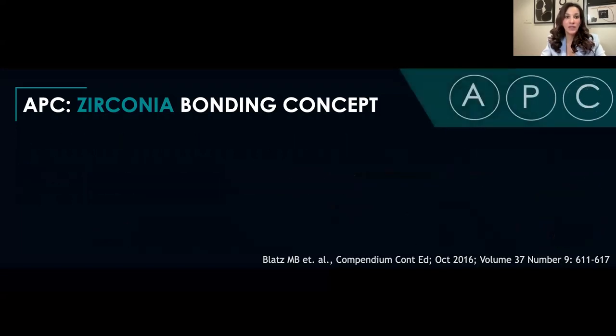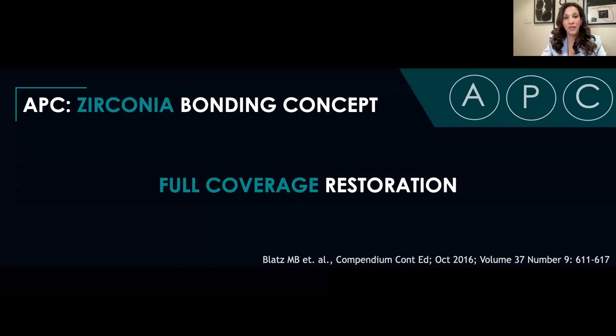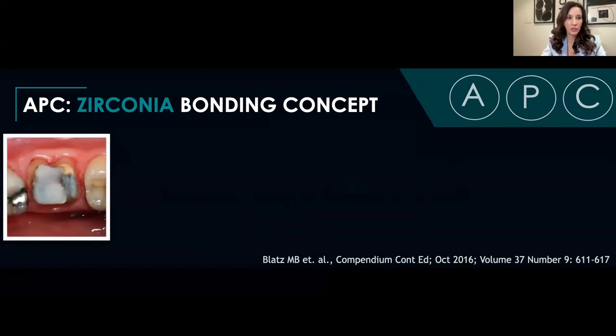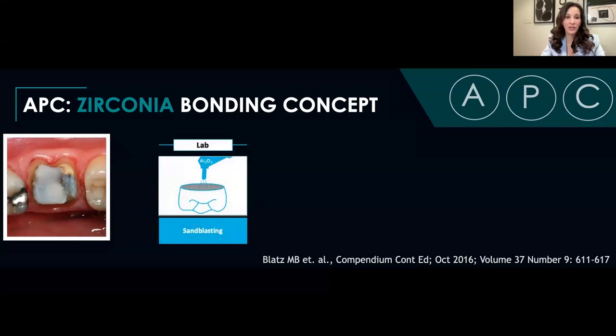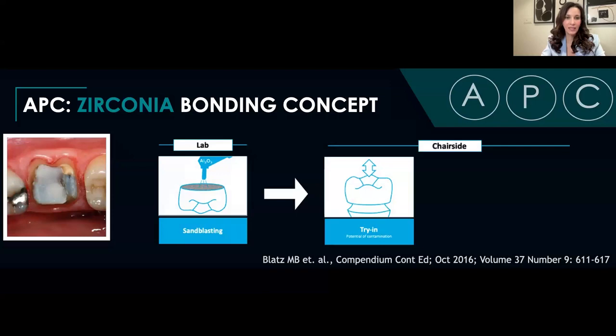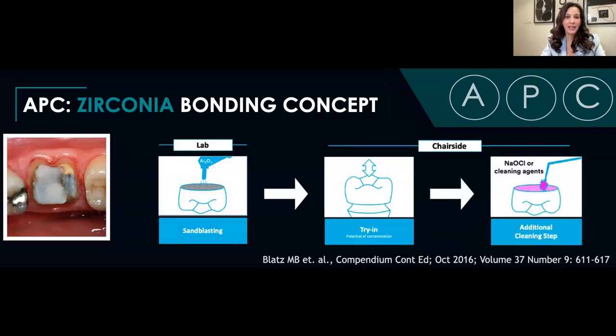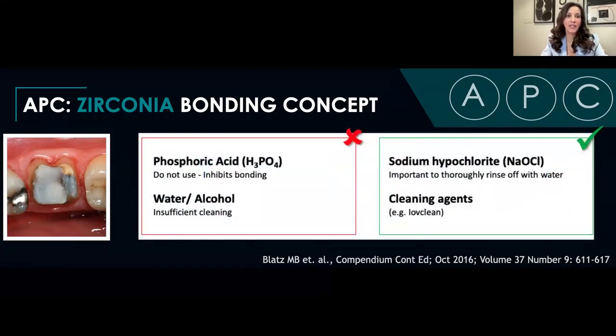So to finish off the lecture, let's look at some cases where we used this technique to bond restorations. So our full coverage restoration. You need to clean off your tooth. The restoration itself has to be sandblasted, and then you can try it in and then clean it off with sodium hypochlorite or a cleaning agent such as Ivoclean. I personally like to try everything in and then I sandblast it after I try things in. And so it's important to understand that you should not just use water, alcohol, or phosphoric acid to clean the intaglio of the restoration. You want to use either sodium hypochlorite or cleaning agents such as Ivoclean.